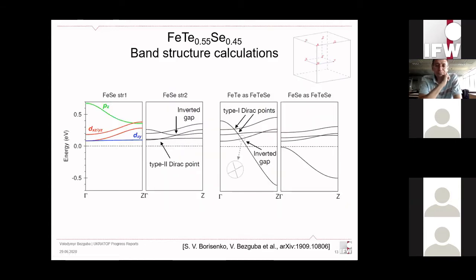But there is a big complication to this. All calculations for this crystal structure are approximations due to the large size of the unit cell. And it turns out that it's very, very sensitive to which approximation you use. So as you can see on this slide, there are 4 different calculations. They are all for iron tellurium selenium, but they give a completely different picture, a completely different scenario. And indeed, in the second one and in the third one, we do get inverted gap opening, and we do expect the surface states. But these are calculations, and it's interesting what is in reality, what is in the experiment.